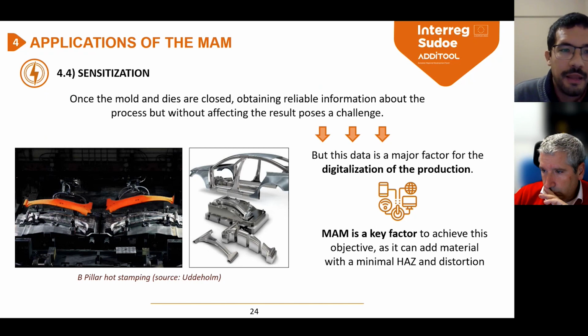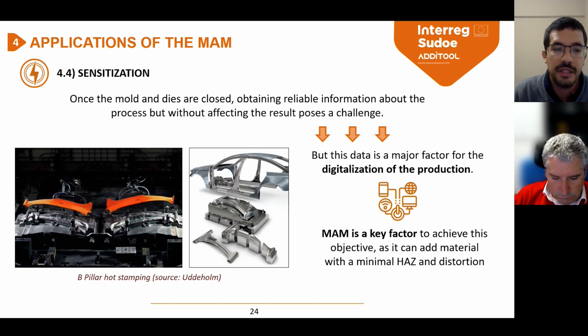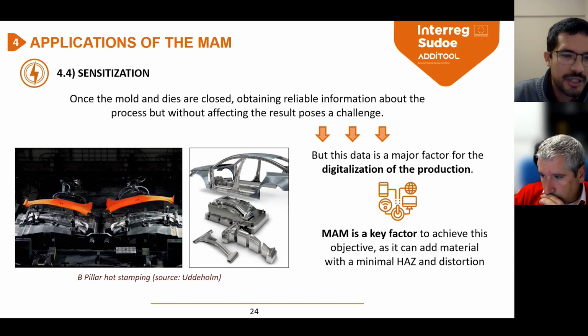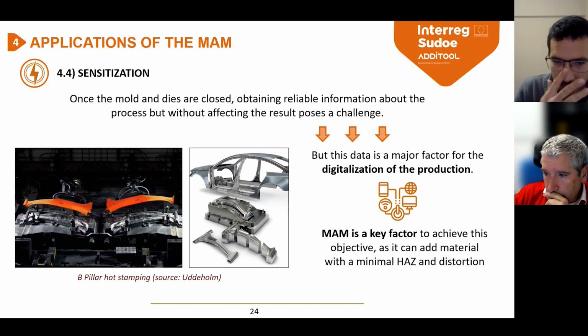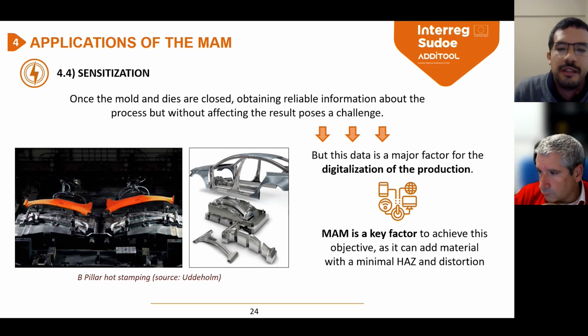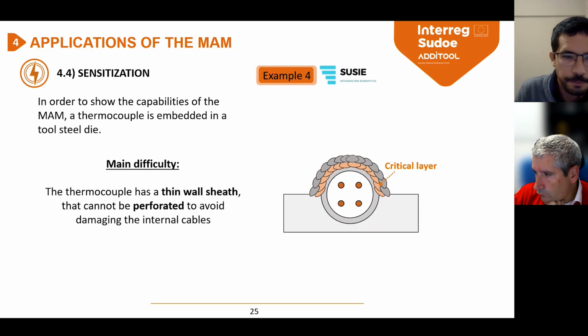And the final application corresponds to the sensitization of the tools. As I have already introduced previously, extracting information from inside the dies and molds when they are closed is quite complex, mainly because when we introduce a thermocouple, for example, we are also going to affect the thermal behavior of the tools. But obtaining this information is necessary in order to digitalize the manufacturing process. And we think that the additive manufacturing process is one of the key factors in order to achieve these objectives.